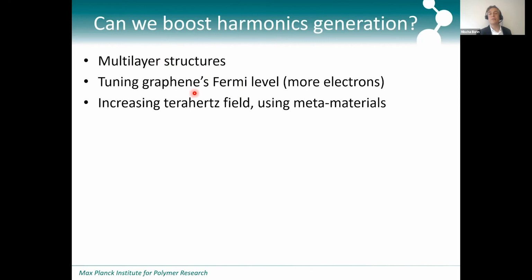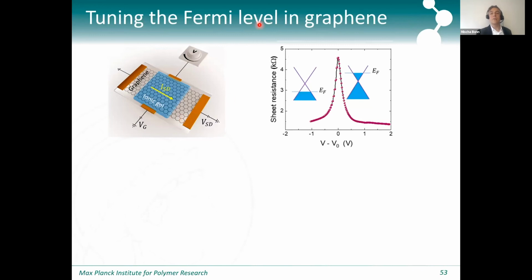recently, is to tune the Fermi level of graphene. So if there's more electrons, we can induce a higher nonlinear current response to the driving field. And the other thing is we could increase, using metamaterials, the incident local terahertz field strength, and thereby increase the efficiency of the process, or rather allow the use of weaker fields. And so one can tune the Fermi level in graphene using this type of gated device.